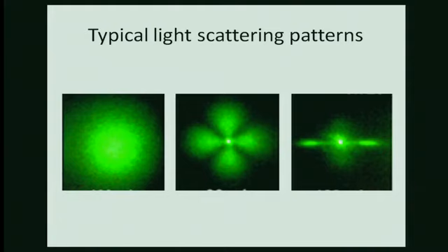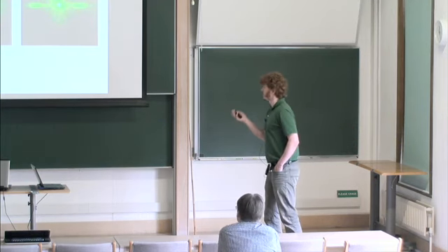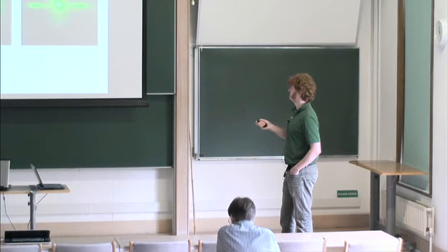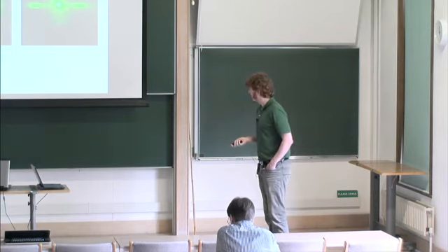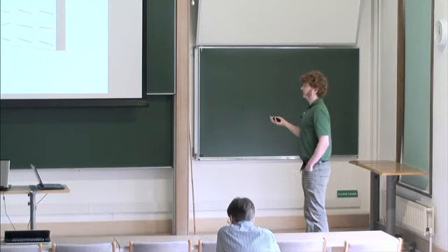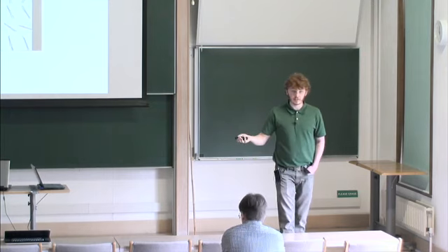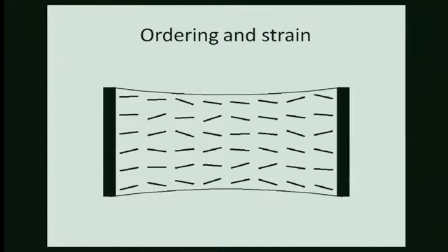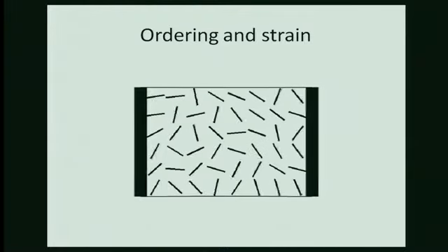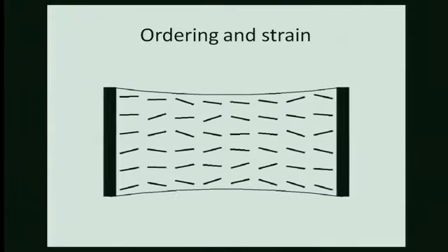The third one is the scattering pattern from a quite well-aligned elastomer, and the one in the middle is something between polydomain and monodomain. From these pictures, we can say that there are some length scales observed in our system, and these peaks correspond to a few micron variation. It's also a known thing that the alignment of the director in elastomers is coupled with strain, and a lot of things are done with that, but that's just to mention.